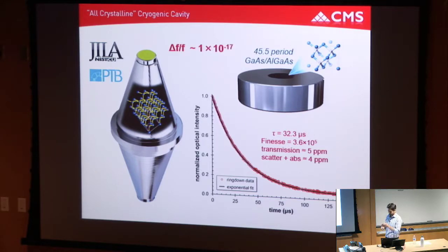So that's a very nice point of stability. And this thing at 124 Kelvin would have a fractional frequency instability on the order of 1 part in 10 to the 17. So it's either a single-digit millihertz or sub-millihertz linewidth laser, at 1 second of averaging. So it's really incredible. And that sapphire cavity I showed earlier goes even better, into the part in 10 to the 18. So if you're looking at the coherence time of these lasers, it's minutes, right?